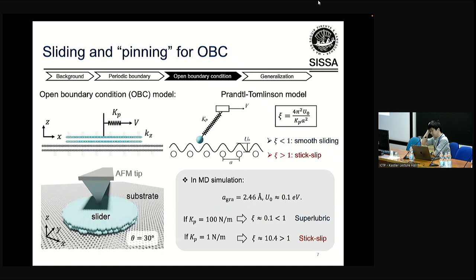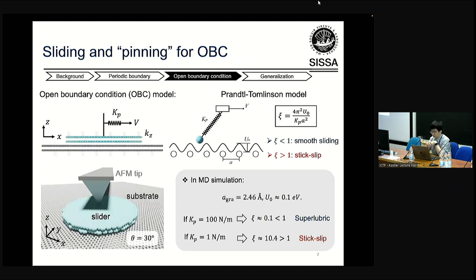So far we have talked about bilayer graphene with periodic boundary conditions, but in real nature everything is finite sized. We switch to finite-size simulations. The lower-left plot mimics the experiment setup, and our simulation setup uses four-layer graphene. The lower two are infinitely large, mimicking the substrate; the upper two are finite size, mimicking the slider. All of them have z-directional springs to mimic the normal elastic modulus of graphite. The slider is dragged by a pulling spring with spring constant kp sliding at constant velocity v. To some extent our simulation model is similar to the Prandtl-Tomlinson model.